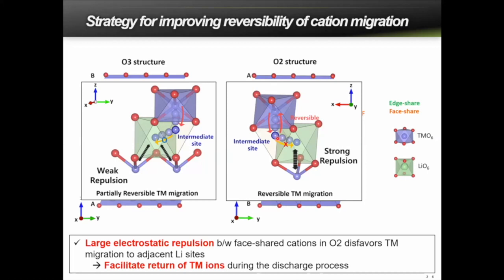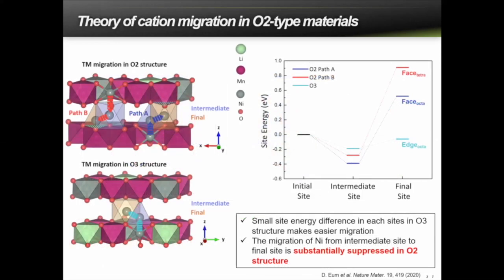This difference in the stability of the octahedral site arises from, of course, the different stacking sequences of the O2 and O3 layered structures. This argument could be supported by our first principles calculations on each site. As we can see in the graph showing the relative site energy of the transition metal, the transition metal in the original O3 structure can easily go to the intermediate site and finally ends up at the octahedral site with a negative energy slope. On the other hand, in the O2 structure, the transition metal can hop into the intermediate site, but it cannot further migrate to the neighboring octahedral site because of its high energy barrier.